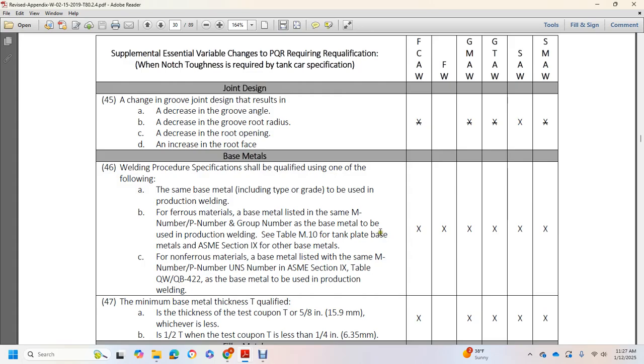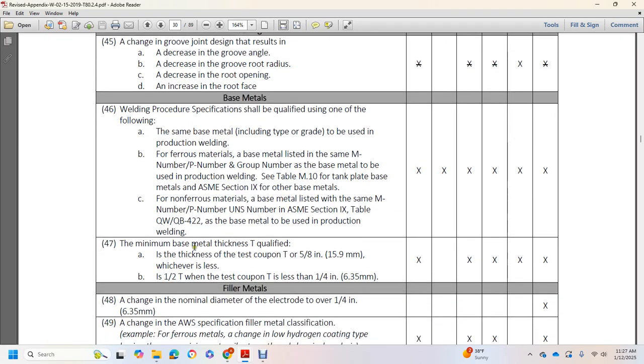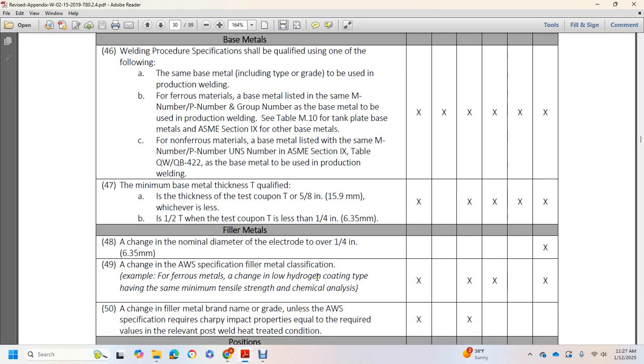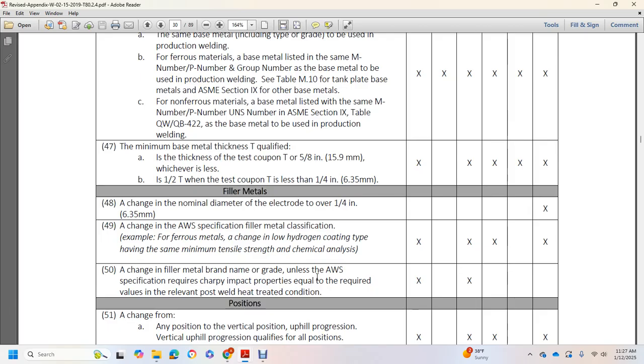See table M10 for the tank plate. Base metals are listed in ASME Section 9. For non-ferrous base metals listed in the same P number or UNS number, see ASME Section 9 table QW-422, the base metal to be used in production welding. Minimum base metal thickness T: minimum plate thickness is the test coupon thickness or 5/8 of an inch, whichever is less, or half the thickness of the thinner plate when the test coupon is less than 1/4 of an inch. Filler metals: change of the nominal electrode diameter over 1/4 of an inch.